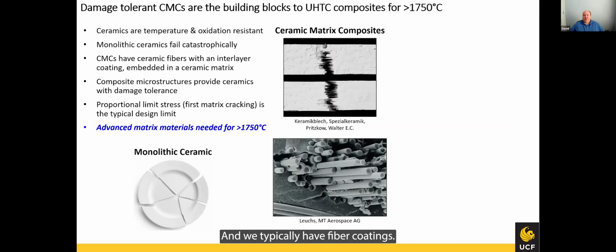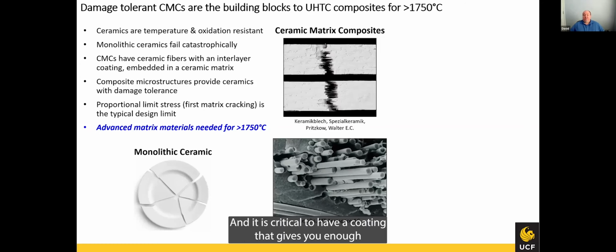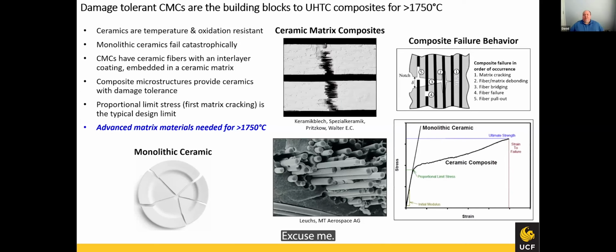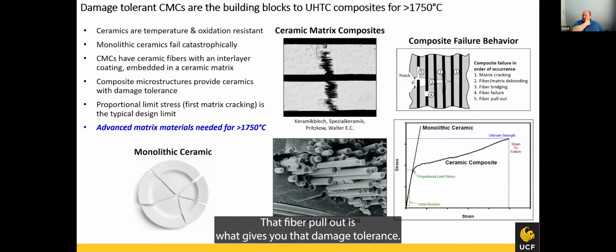And we typically have fiber coatings, and the fiber coatings are where I would say 80% of the technology is, and it is critical to have a coating that gives you enough connection to get fiber pullout. Excuse me, we'll look at composite failure behavior. That fiber pullout is what gives you that damage tolerance.